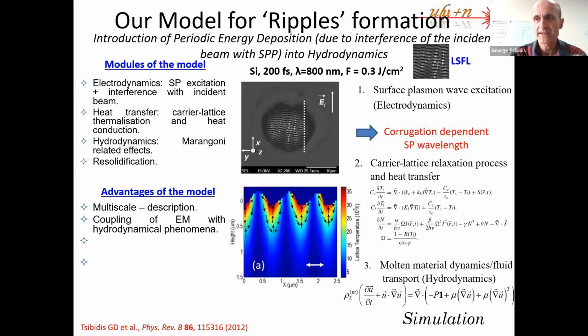The solidification of the material occurs after some nanoseconds. Okay. And then there is solidification. After that, the lattice temperature goes below the melting point. So it freezes, it goes, for example, some milliseconds to the initial thermal state temperature. But the profile, the topography stays like this, for example. So is there any aging effect? If you wait for days, let's say, in the structure? No. It's very stable. Yes.